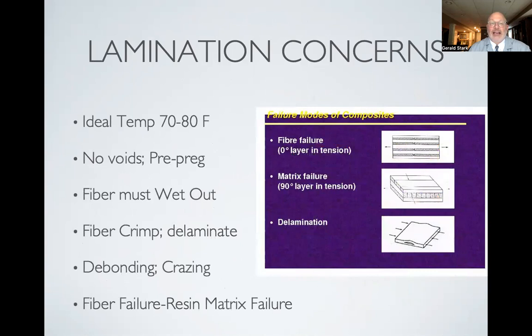So when we're laminating, we try to make sure that we don't have any voids. We try to make sure we wet everything completely, and we need to avoid any sort of debonding or crazing, because once the resin breaks down, that's the real challenge with composite. Once you see voids, once you see cracks, then they'll begin to propagate, just like cracks in your windshield, right? And unless you bond them, they'll continue to propagate, and that's called crazing.